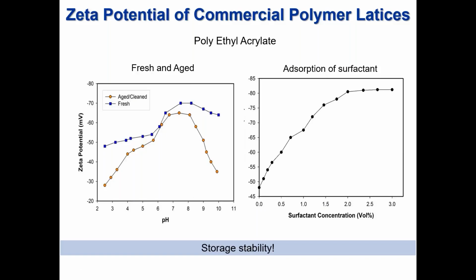replacement. The initial zeta potential in milli-Q water at pH 5.6 was about -48 millivolts, and the latex was titrated with a linear long chain C14-18 sulfonate, and the process followed directly using zeta potential measurements. It's clear that the latex surface was not initially fully covered with surfactant. The final zeta potential increased by almost 70% to -80 millivolts, which would provide much greater tolerance to mechanical and